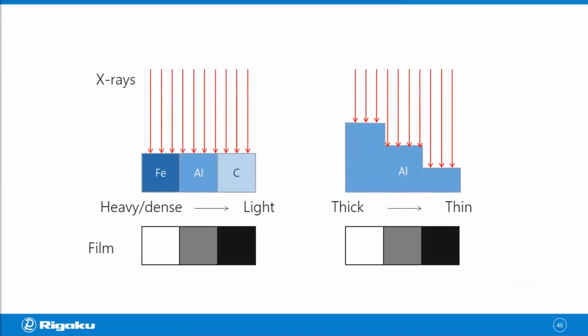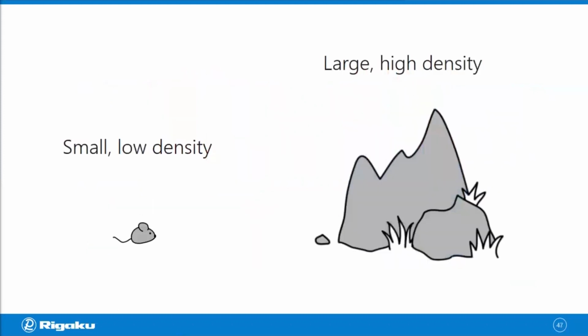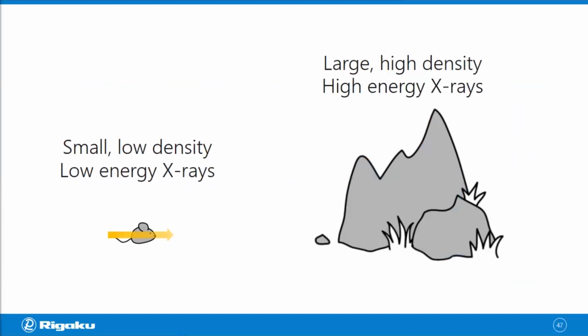So what this means is, if you want to look at a small, low density material and get a good image, you want to use low energy X-rays to make sure that your small, low density sample would absorb enough X-rays. If you want to look at something large or high density, you're going to need high energy X-rays to make sure that at least part of the X-rays would get through it. So that's the rule of thumb.